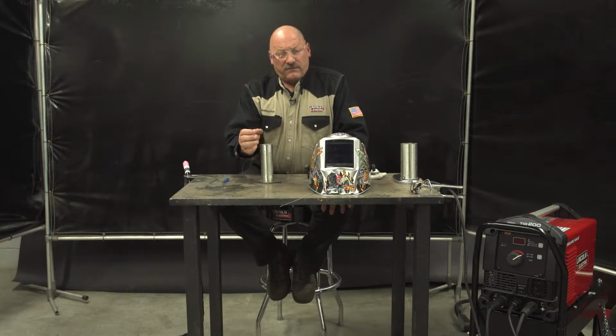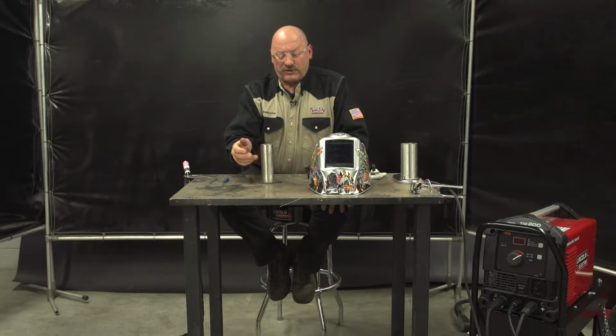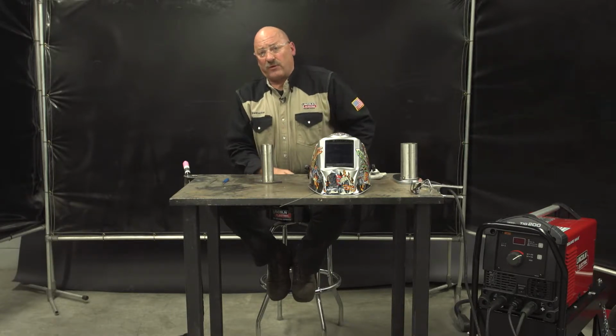When you weld on a non-hardenable grade of stainless steel like 304 stainless or 321 stainless, the weld deposit needs to be a non-hardenable, austenitic stainless steel weld deposit. But if you're welding to a carbon steel with a carbon steel filler wire, what you're actually going to have is a weld made from steel alloyed with a little bit of chrome and a little bit of nickel from the stainless. And it could harden up to a very brittle microstructure and fail later in service.